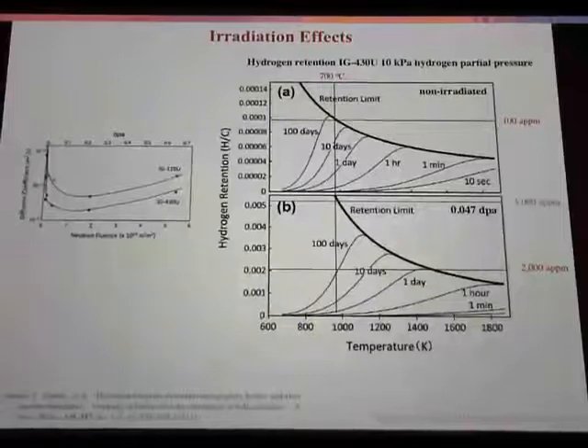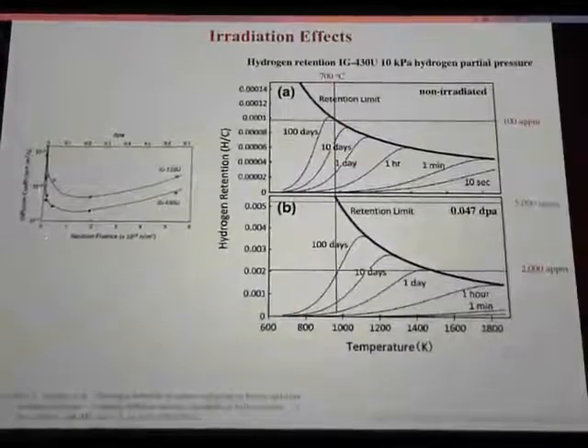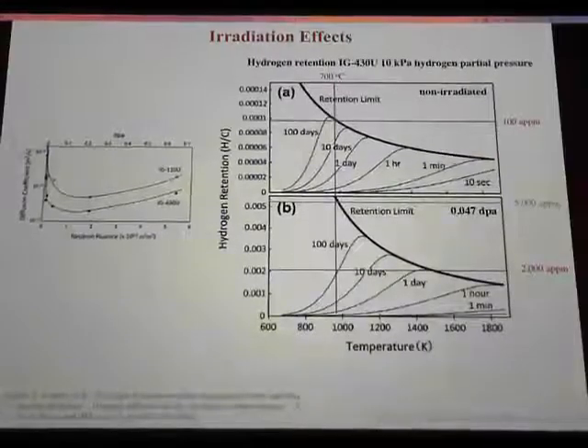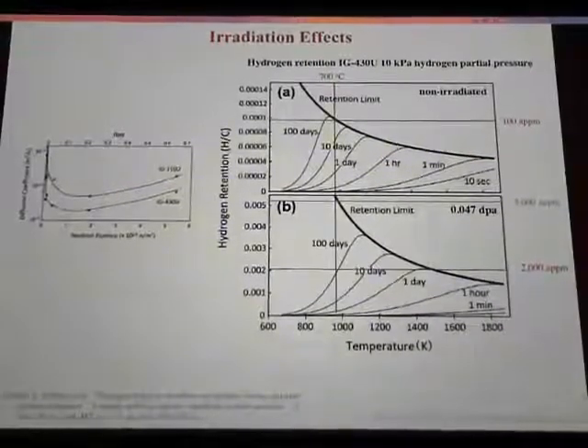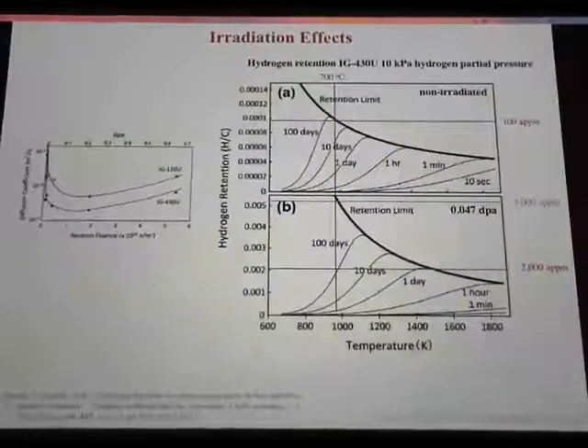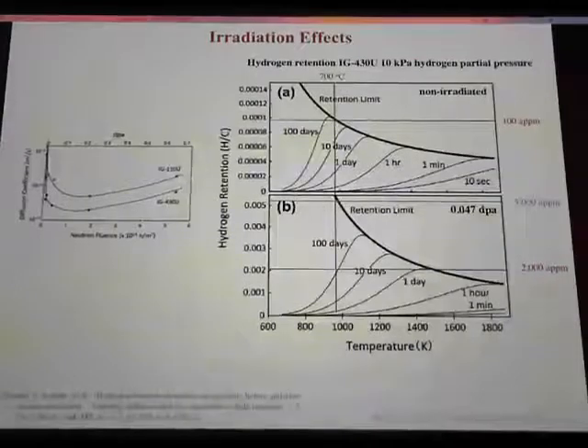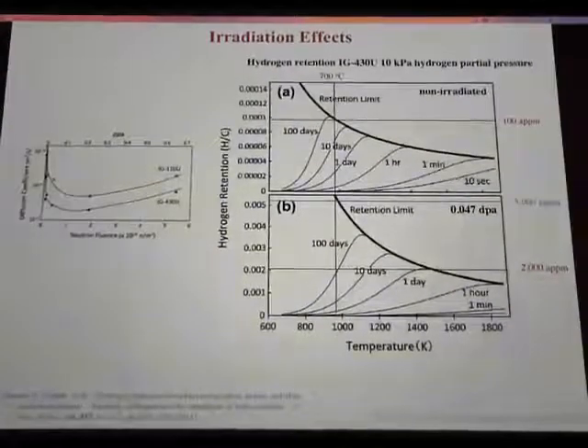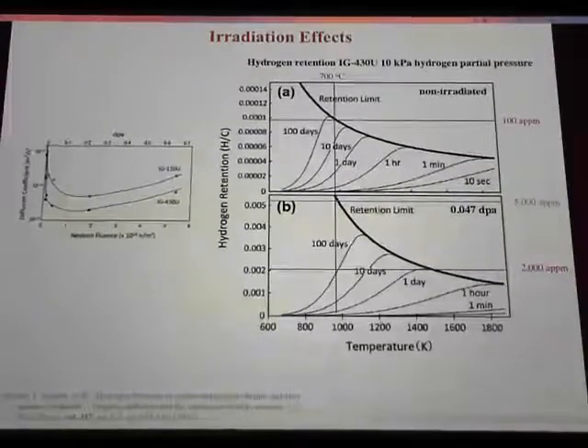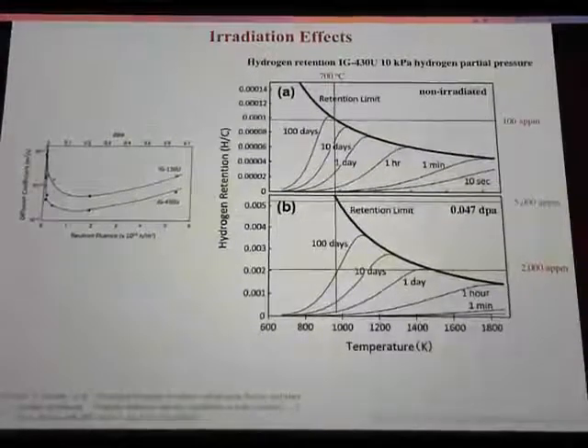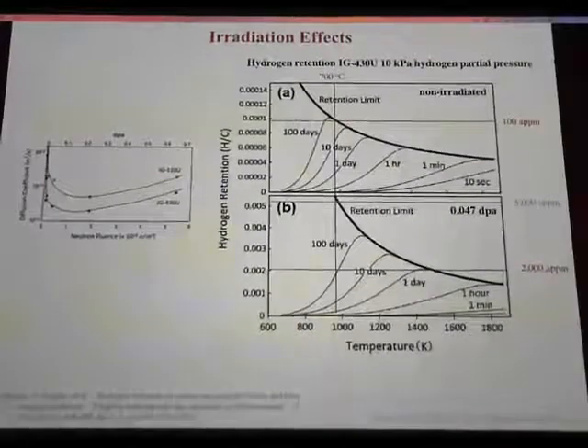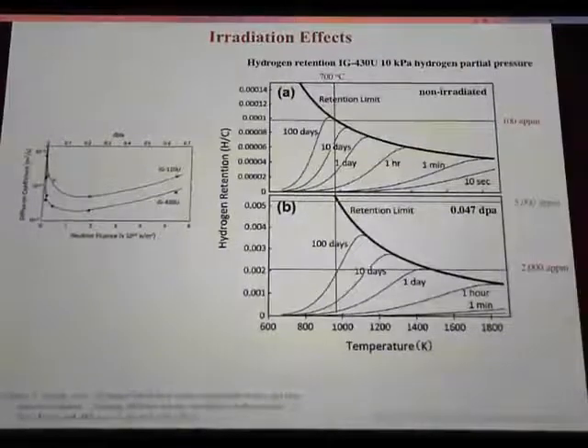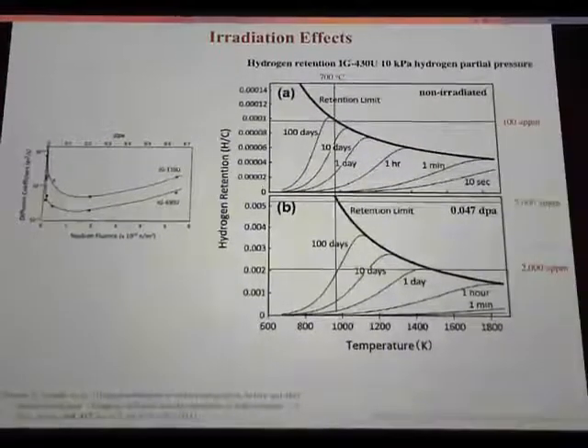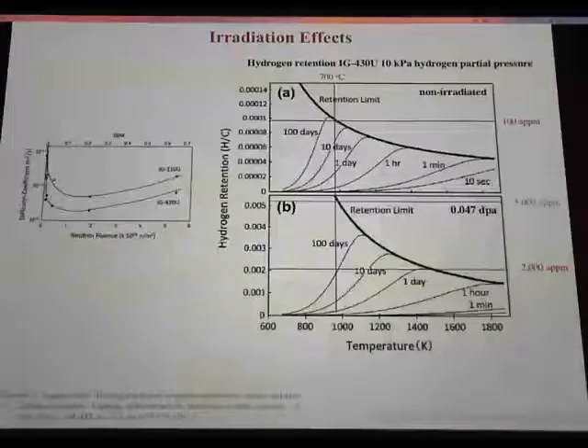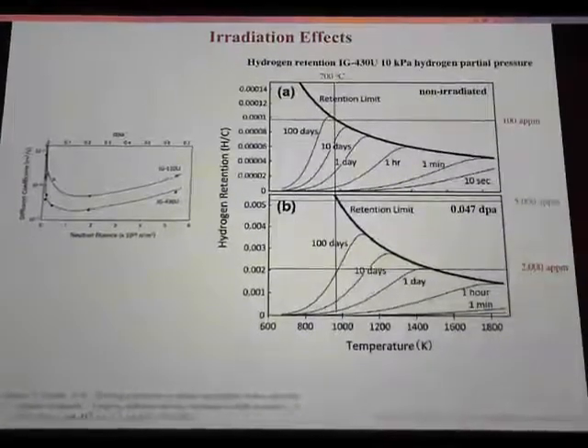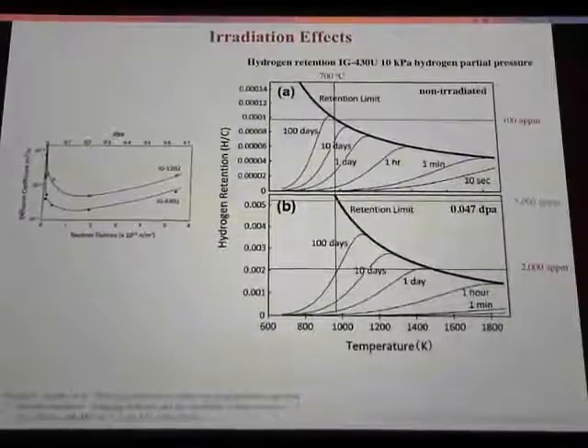Another thing to keep in mind is that the diffusion coefficient and the trapping site density evolve with irradiation. And so doing measurements on non-irradiated graphite is probably very incomplete in terms of having the full picture of the lifetime of each fuel element. And so what's important, however, is to understand mechanistically what are really the microstructural parameters that you care about for the graphite in order to then predict the trapping site density and the diffusion coefficient. And then that's the mechanistic side, and at the same time you need to push the engineering too and just irradiate some graphite and measure how much and how fast it absorbs.